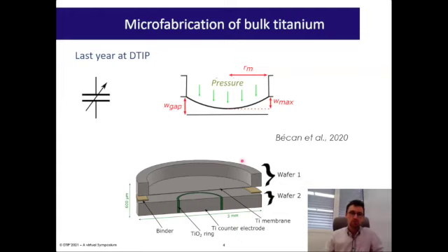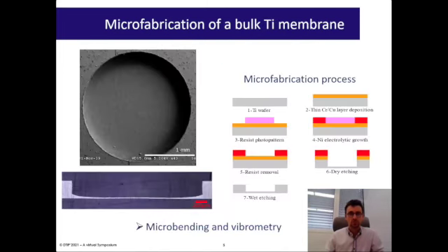So here you have wafer one, that's our titanium membrane. And you have a titanium counter electrode here, which is isolated from the rest of the substrate by a titanium dioxide ring, which is an insulator. The two wafers are then bonded together to form the pressure sensor. Here I'm going to talk a little bit more about the membranes, and here are some pictures of the obtained membranes.